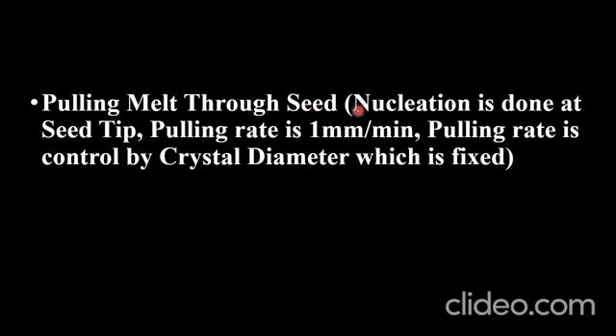You should know that when the seed is pulled upward with respect to the melt, that can cause nucleation. Nucleation is basically done at the tip of the seed, because the seed material is in solid phase, whereas the melt is in liquid phase. So the temperature of the melt is higher than the seed. Due to this, heat will start to flow from the melt toward the seed, and the temperature of the melt at the point where the seed is connected decreases, resulting in conversion of the melt into a solid. This solid is a single crystal which is pulled upward, and in this way continuous single crystal formation is done.